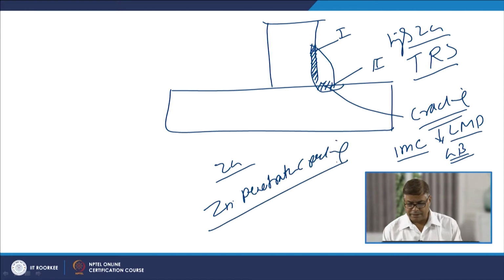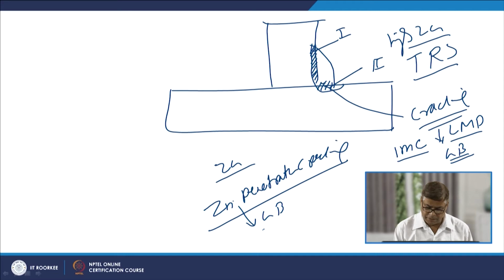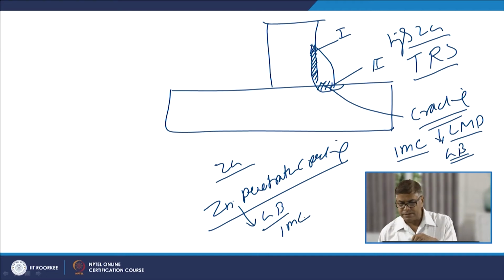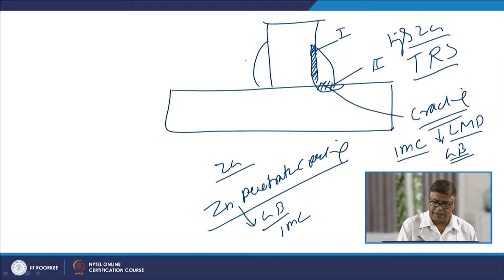Zinc penetration cracking is basically due to the localized presence of zinc at the grain boundaries, formation of the IMCs, and in presence of the tensile residual stresses, especially in case of the fillet welds, leads to the increased cracking tendency, and this is what is typically termed as the zinc penetration cracking.